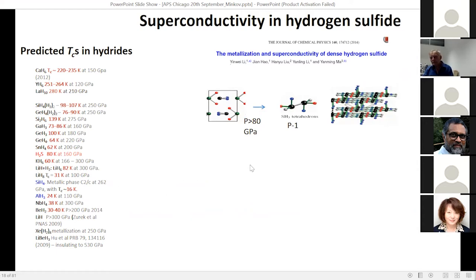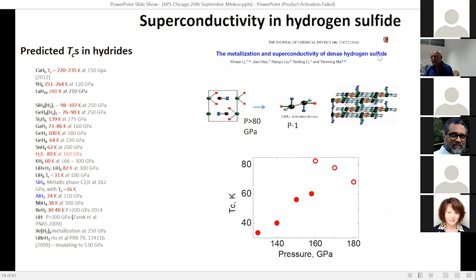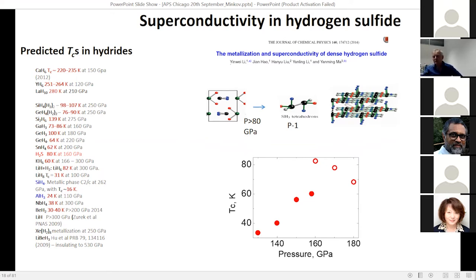We started with hydrogen sulfide, which is not the most representative choice. This demonstrates how experiment works — it's not blindly following predictions, and there are many uncertainties. Selection was influenced by my collaboration with Yanming Ma on transparent sodium; I knew how carefully he works. Predictions for H2S were not very high — around 80 GPa and 80 Kelvin — and hydrogen sulfide is difficult to work with experimentally.